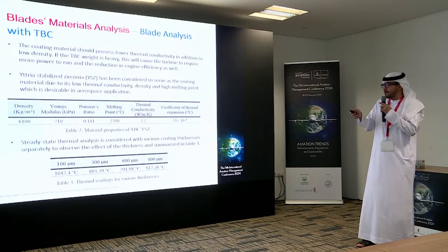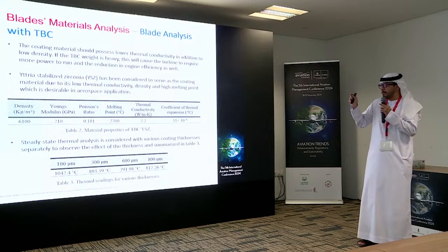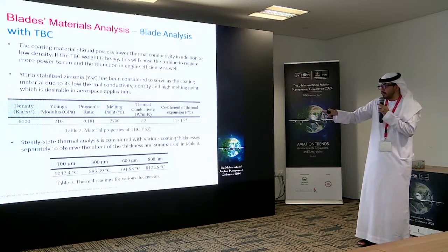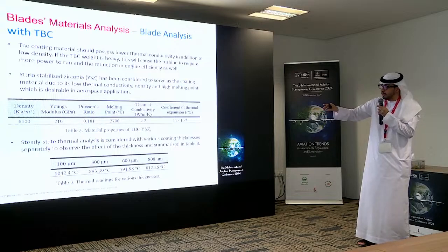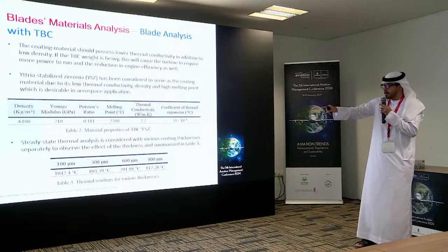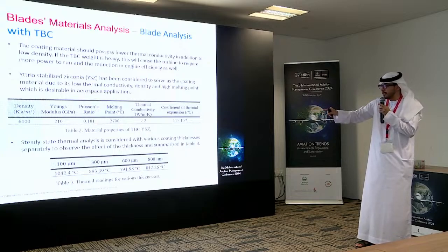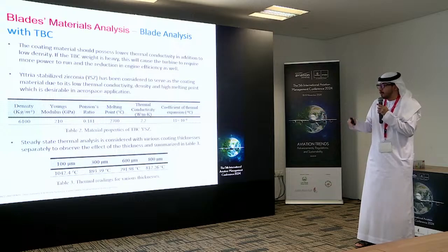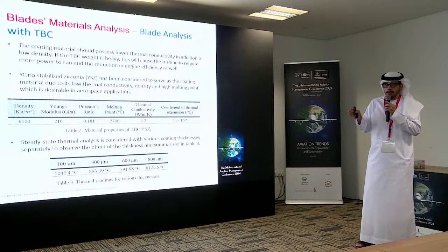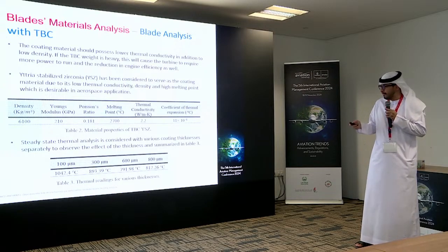After we applied the thermal barrier coating on the blade itself, the Incoloy 718, we applied several thicknesses for the coating, which is summarized in table 3. Please notice that we applied 100 micrometers up to 800. Those are chosen results. You will notice that the more we increase the thickness, the more the temperature decreases, and we can see a significant decrease in temperature, which proves that the coating material is isolating the heat due to its lower heat conductivity.